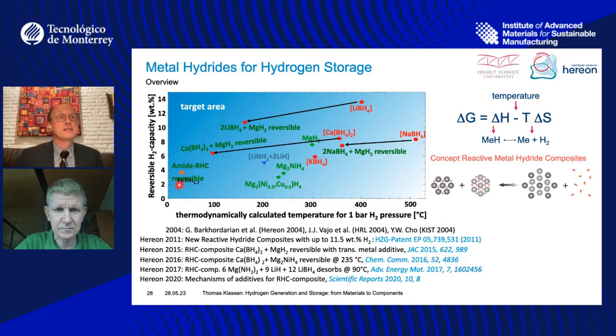So yeah, there are some metal hydrides that are known for a long time, like for 3 decades, as you said already. So like iron titanium. Iron titanium absorbs hydrogen easily and releases it again at room temperature. However, because iron is quite heavy, has a high density, the weight-related capacity is only 1.9%, so very low.